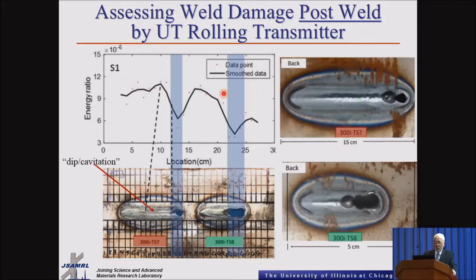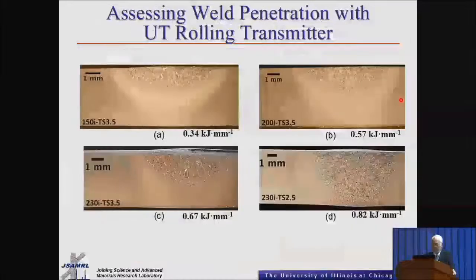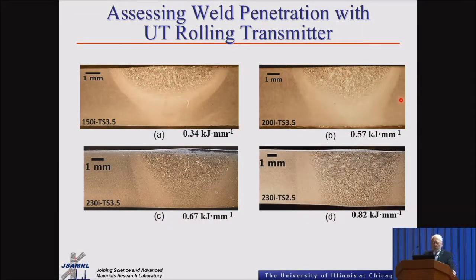When it came to the real burn through at the higher heat inputs, in the 300 amp welds, you can see that there was a big drop in the energy ratio in both welds. Again, this correlates with what we had called burn through, because you also have the hole being produced. So now you say, is it possible for us to assess the penetration using the UT rolling transmitter? I'll show you these four welds using four different heat inputs. In these two welds, you can see almost the same penetration. And here you have full penetration in both welds, more so in this one for the highest heat input, compared to this one in C.